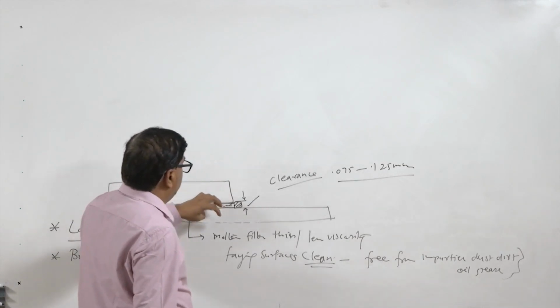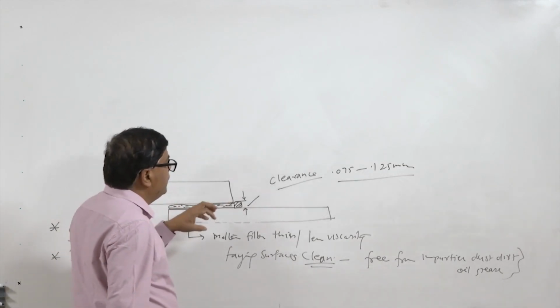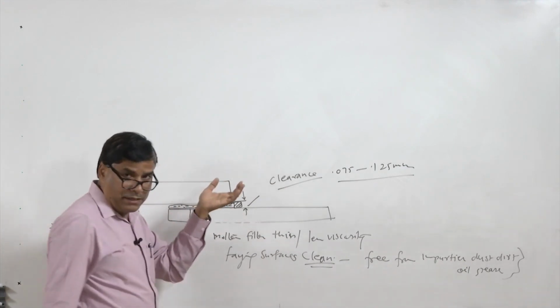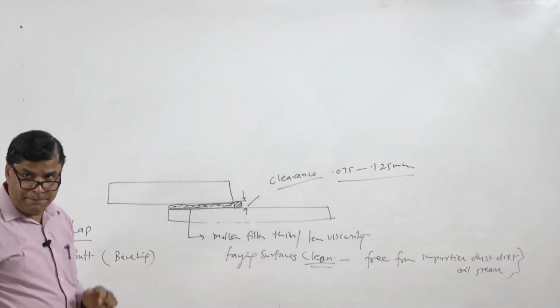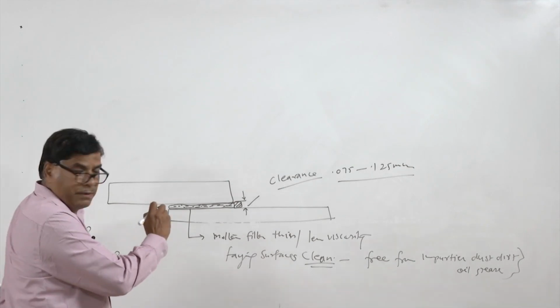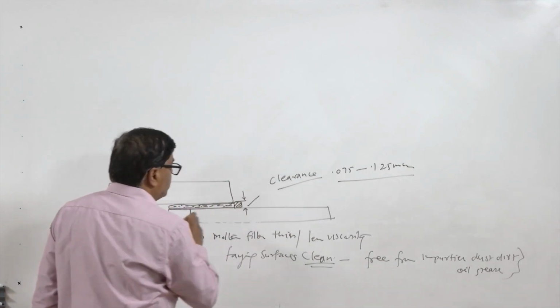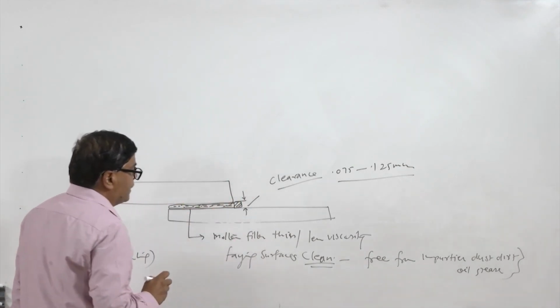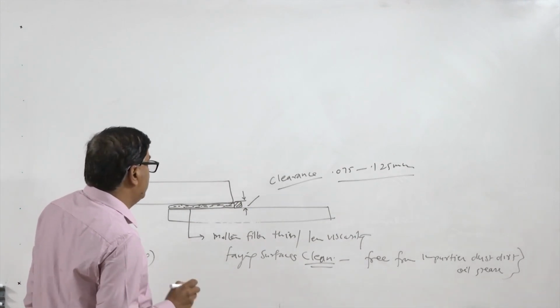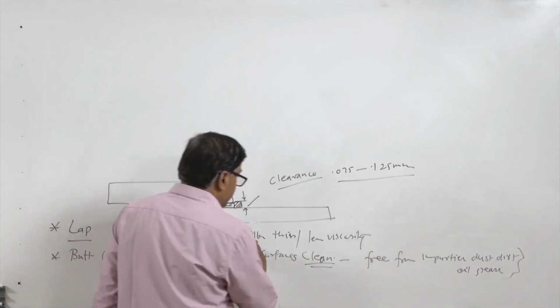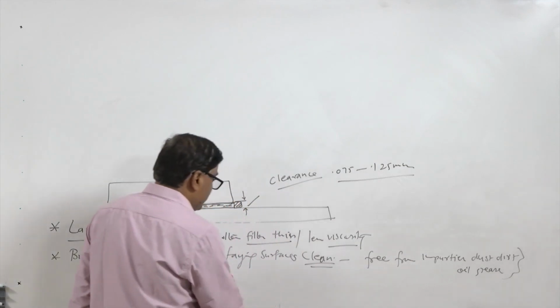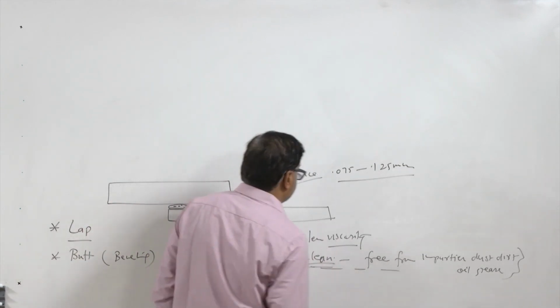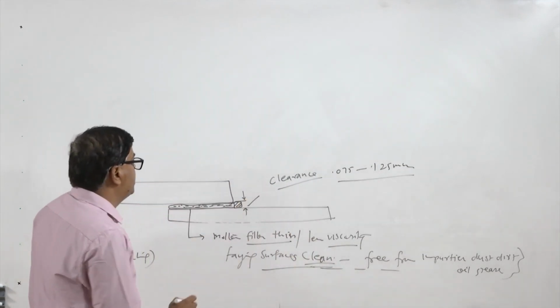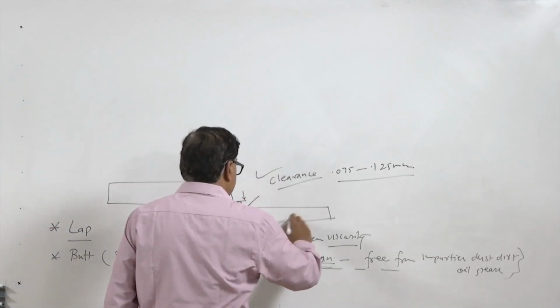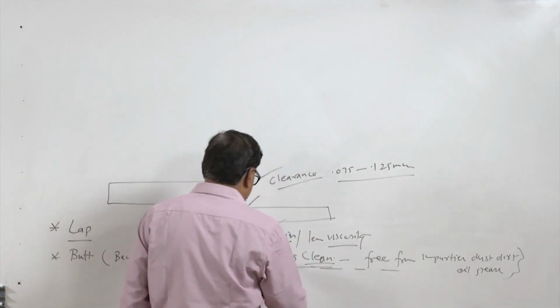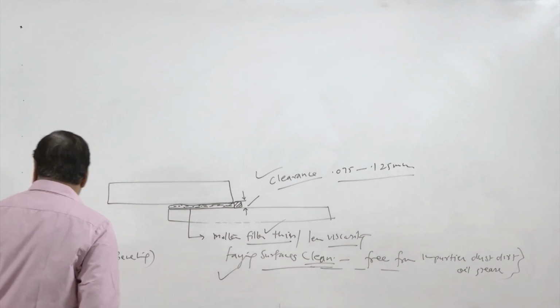Once it has become hot, the filler metal is applied. The filler metal, either brazing or soldering material, will be brought to the molten state. So, it will be sucked in by the capillary action between the components. It will be sucked only if it is thin enough and less viscous, and the surfaces are very clean, and if the proper gap is maintained. So, the gap, the thinness of the material, as well as proper cleaning of the faying surfaces are very crucial for